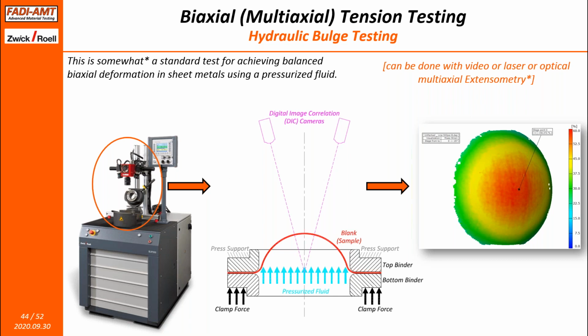You use the same kind of machine, again, as we showed before, like a BUP machine or a metal forming machine, and you just replace the tooling from mechanical tooling to hydrostatic, basically bulging. And with DIC on top of it, we can monitor the evolution of the shape of the sample as the test progresses. And just like before, you can do this test with DIC or without DIC.